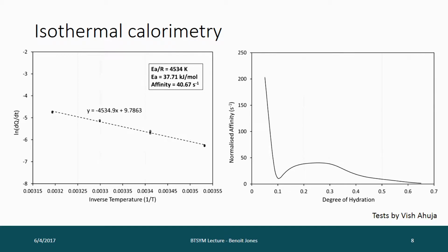So how we get the activation energy and normalized affinities, we can do isothermal calorimetry, where small samples of either cement paste or mortar are put into the isothermal calorimeter, and they're kept at a constant temperature, and it measures how much heat has to be taken out of the samples to keep them at constant temperature. Because it's an exothermic reaction, you need a little bit of energy to make each chemical reaction occur, but when they happen, they give off even more energy. So on the left, you can see this plot, which is tests at different temperatures, and basically the gradient of it gives us the activation energy.